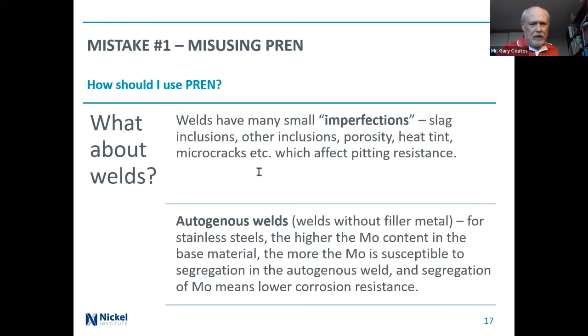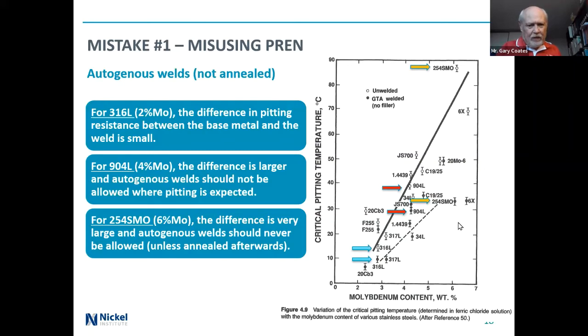Many of you are familiar with the curve that was generated years ago, when I was a young corrosion specialist, by a friend of mine, Dr. Andrew Gardner, where for 316L, the blue arrows here, the top line is the unwelded sample, so the base material unwelded. The intermittent line here is the autogenous weld resistance. So for 316L with 2% molybdenum, the difference between the base metal and the autogenous weld is small.